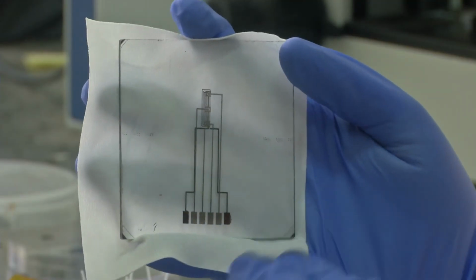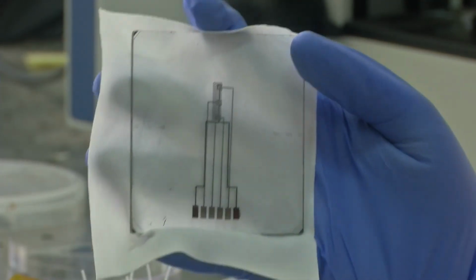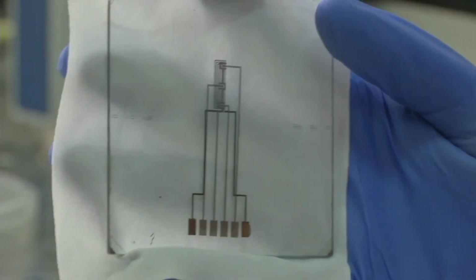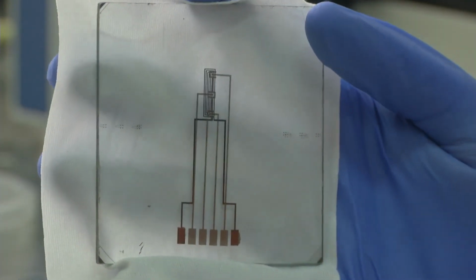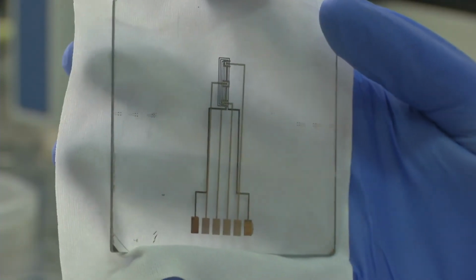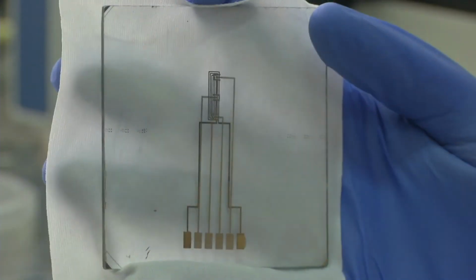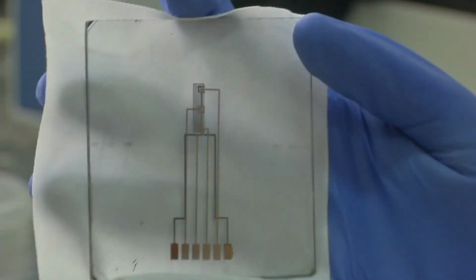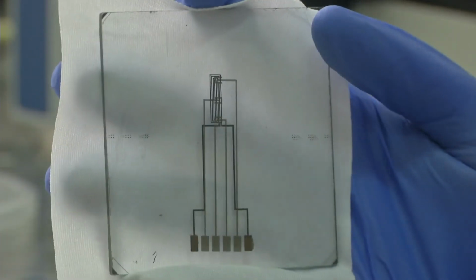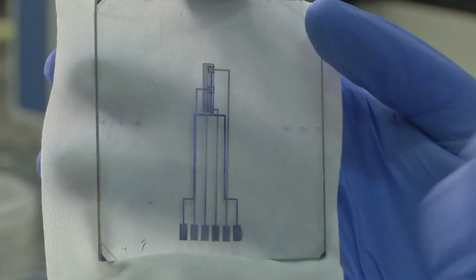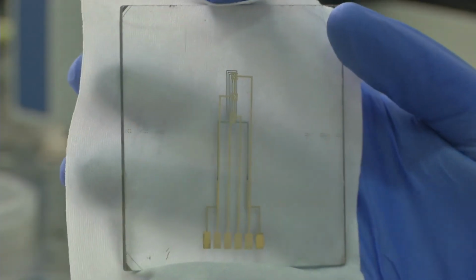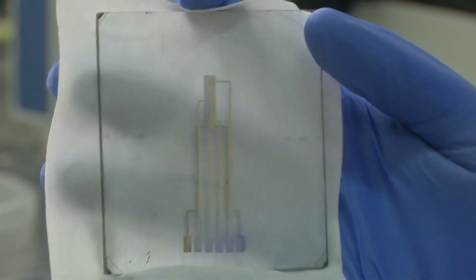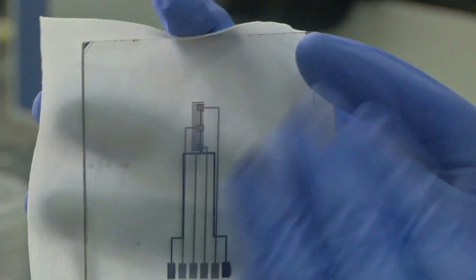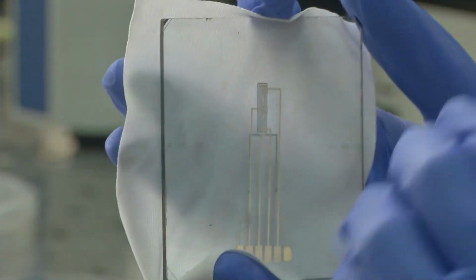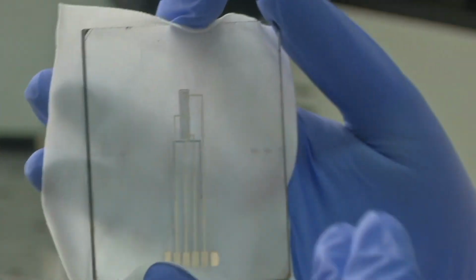We will supply voltage to this micro heater and it will be heated up. It can be controlled to be maintained at a particular temperature, let's say plus or minus 0.5 degree. So between 36.5 and 37.5 degrees, this heater's temperature can be maintained, or even closer depending on how accurate your control system is. The cells will be flowing like in the previous microfluidic channel, but the cells will also feel the 37 degrees Celsius, which is the internal body temperature. So we are recreating the in vivo scenario in this microfluidic platform. As a result, whatever sensed data comes out will be closer to an in vivo measurement.